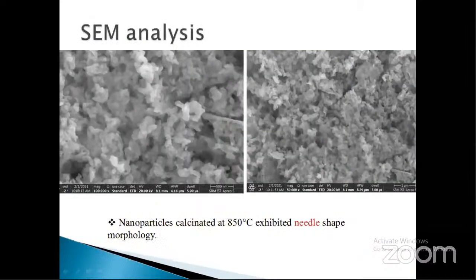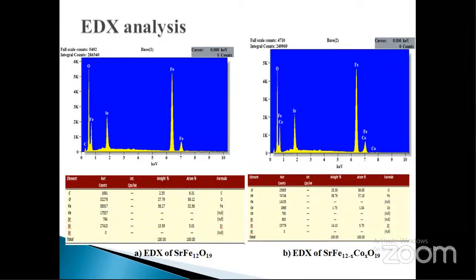And this is the SEM analysis. The structural and morphological studies were done using SEM analysis, and the nanoparticles calcined at 850 degrees Celsius exhibited needle-shaped morphology. And the elemental composition was studied using EDAX analysis. The spectra verified particles without impurities and a good match with the stoichiometric amounts of elements in the nanoparticles.